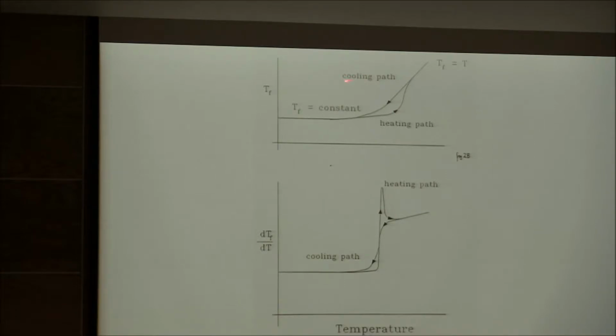And what you see is that the cooling path, which has the arrow going down, and the heating path at the same rate, which has the arrow going up, are very different in where the density will be. It means there's hysteresis here. It means there is a path dependence of the state of the glass. And that is the key. If we know that there is a path dependence of the state that we're investigating, then we know we can get kinetic information from that state. That is the message. Okay?